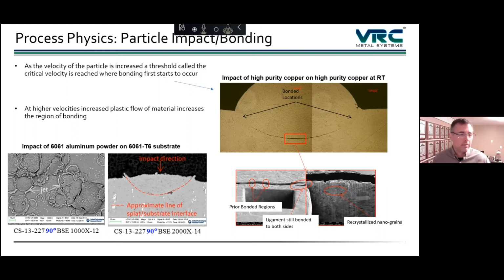Now, if you look at the bottom left, you can see an aluminum particle impacting on an aluminum substrate, and there's much more severe plasticity. So this is at a much higher velocity. And you can see that the interface is completely consumed, and there's jetting of material outward from that interface. And that's what happens when you get a very good high quality bond, which is what we're looking for.